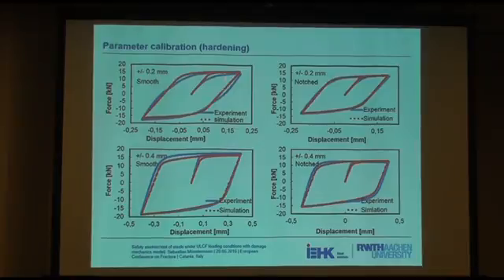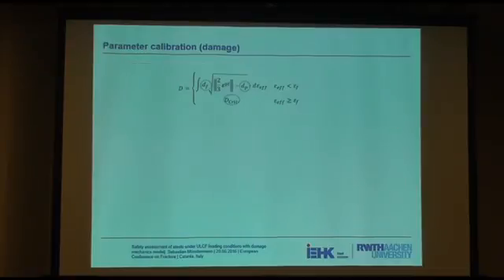There is already quite a good agreement between the experimental and numerical results in this case, but please consider that so far the damage evolution parameters were not calibrated, so there is in other words no need to have the perfect match in here, because damage evolution is not considered.